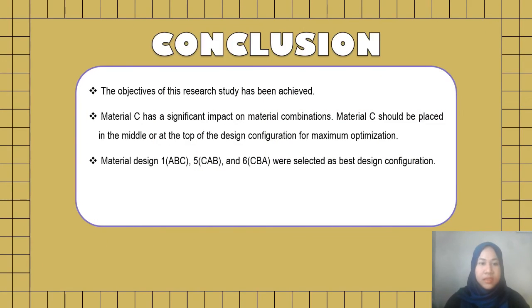As for the conclusion, the objective of this research study has been successfully achieved. It has been discovered that material C should be placed in the middle or top position compared to materials A and B to achieve the best result. Material C has a significant impact on material combinations. Material C should be placed in the middle or at the top of the design configuration for maximum optimization. To sum up, material design ABC, material design CAB, and material design CBA were selected as the best design configurations.